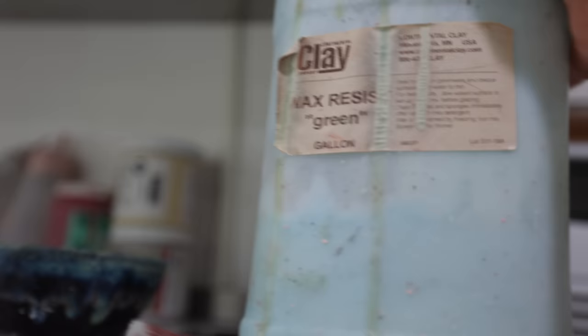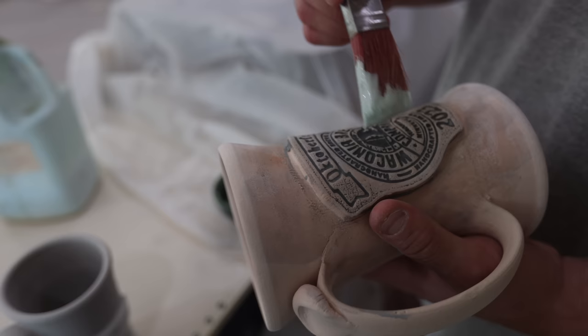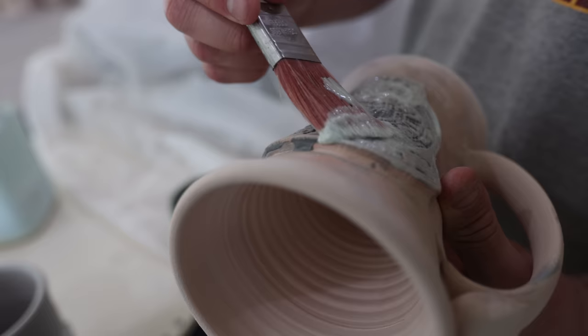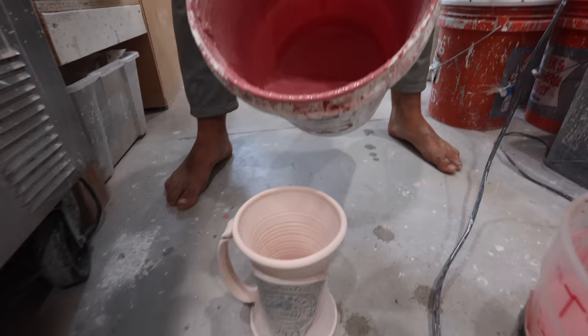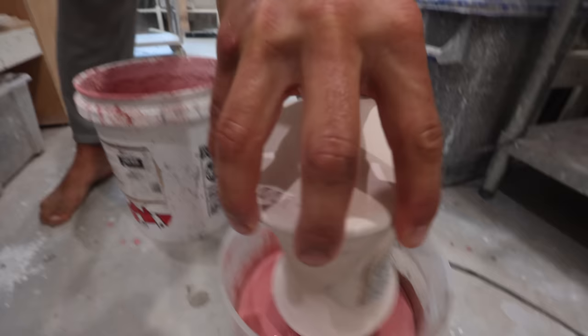This is a really great way to make a logo pop. After we put that glaze in the logo, we have to apply wax resist over top of it — we paint this wax on the top. This wax will eventually burn off at a pretty low temperature, but what the wax does is it keeps other glaze from getting on top of that. So we put the black glaze in and then dip the mugs into different glazes, but we don't want that glaze to cover up the black glaze already in the logo. Now I'm going to dip this in our first glaze, which is Mayco Red — we pour it in first, rotate as I pour out so it glazes the lip, then dip the rest of it in, and the glaze just falls right off because the wax is on there.